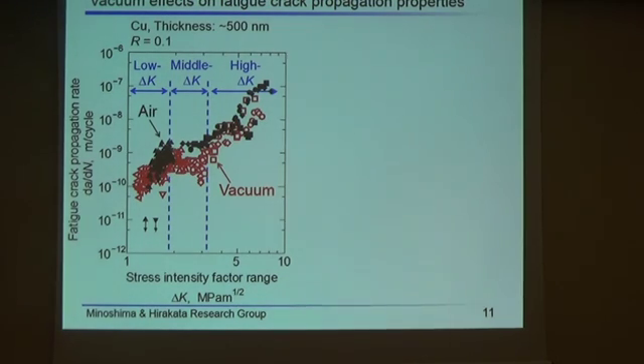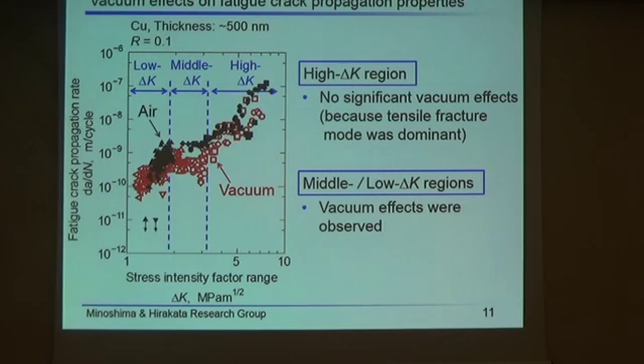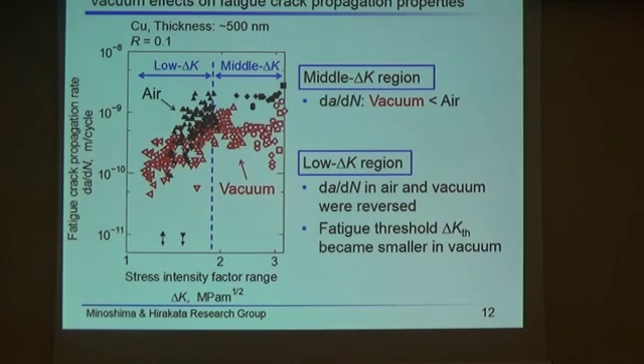Focused on the environmental effects, no significant vacuum effects were observed in the high delta K region. This would be because the tensile fracture mode was dominant in this region. In contrast, in the middle and low delta K regions, vacuum effects were observed. The enlarged view of these regions is shown here.